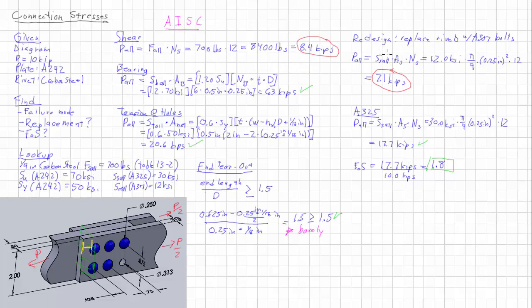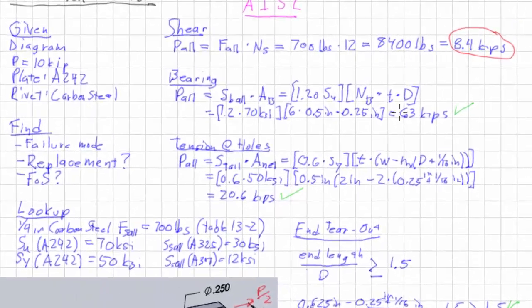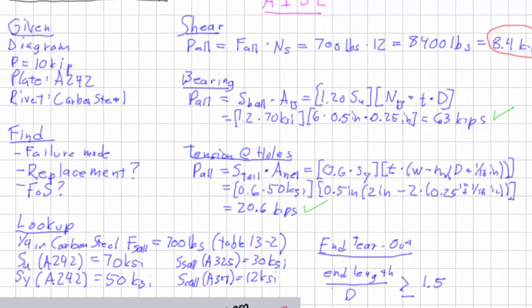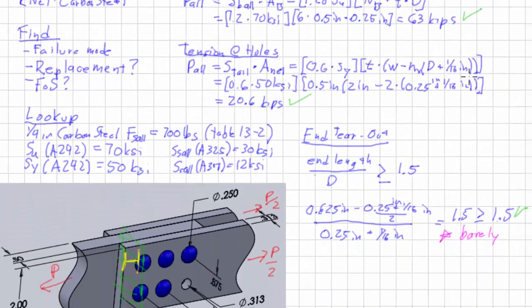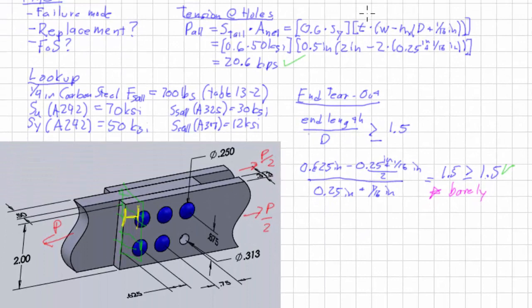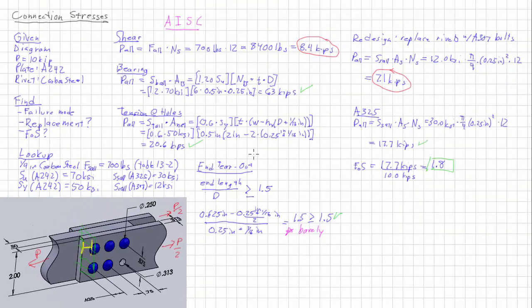So we redesigned it using bolts. We found that the A307 bolt material was actually going to be worse, so we changed our material to something a little bit stronger, and that came out to work out, and our factor of safety was reasonable as well. The tough parts here are making sure you've got all of the necessary information here and figure out what's what. The tension at the holes is a little complicated, but when you remember that all you're doing is subtracting out the hole, you've got to consider the clearance and what exactly is the cross section here. We only have 2 in the cross section. Then again, breaking it down little by little, then putting it all together is the way to success in this type of problem.